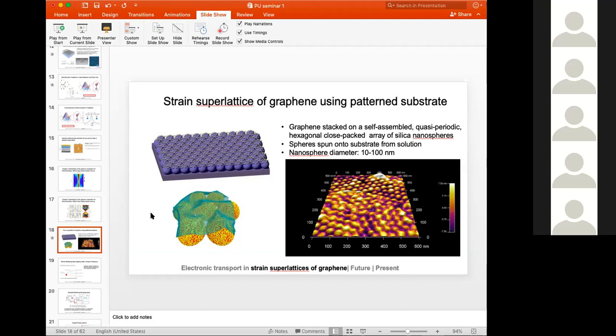For wet transfer, we usually have graphene which is grown on copper foil using chemical vapor deposition, and essentially, the graphene floats on water and we scoop it up with our chip. It requires some skill and time, and sometimes it can go wrong, but it's a wet transfer technique. You can look that up. I'm sorry, I don't have an image of it right now.